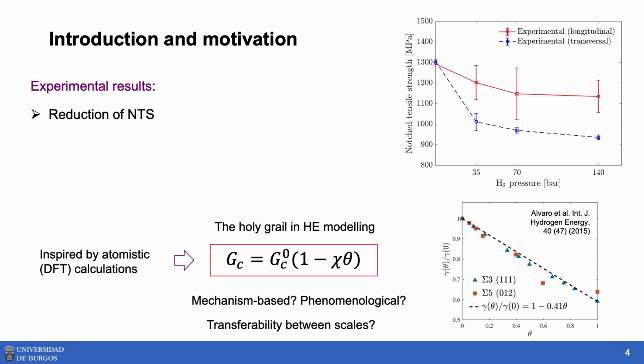I will skip the details of the phase field fracture model, but this is the key point: as in many other damage models, it is capturing the reduction in mechanical properties. It's just the reduction in the fracture energy, or critical strain energy release rate. I call that the holy grail in hydrogen embrittlement modeling, because we have a lot of discussions. We are not coming to an agreement whether we have to be inspired by DFT calculations, based on fracture mechanics testing, or use a phenomenological law and so on. I'm open to any suggestion about how to improve these kinds of laws and how we can be more mechanistic. But we choose this linear reduction because we are inspired by DFT calculations that show a linear reduction as a proportion of coverage of an interface.